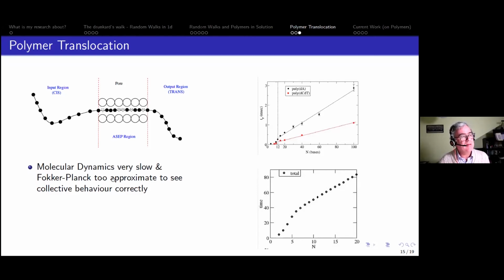And the two methods that existed at the time were either the Fokker-Planck method, where you approximate the center of mass of the polymer as moving in a complicated potential well, but that's too approximate and doesn't see the collective behavior. Or molecular dynamics, where you do an all-atom simulation, and they tend to be very, very slow and only simulate a few nanoseconds of dynamics. So we wondered whether we could, at least in qualitative terms, reproduce the same behavior.